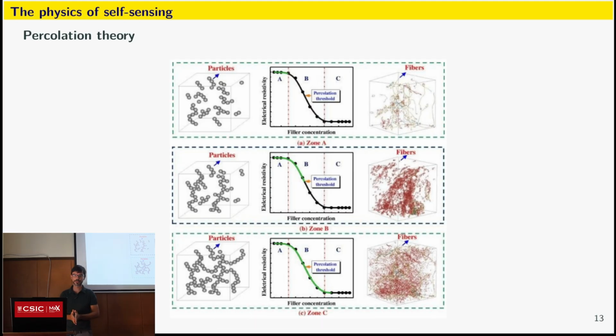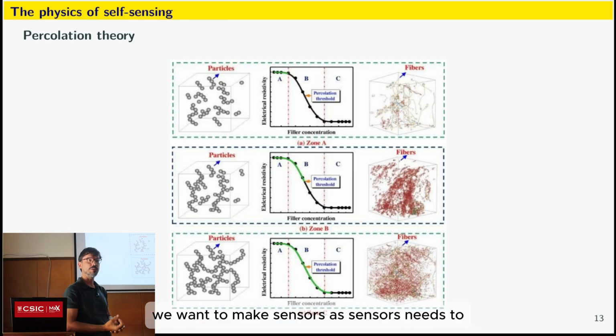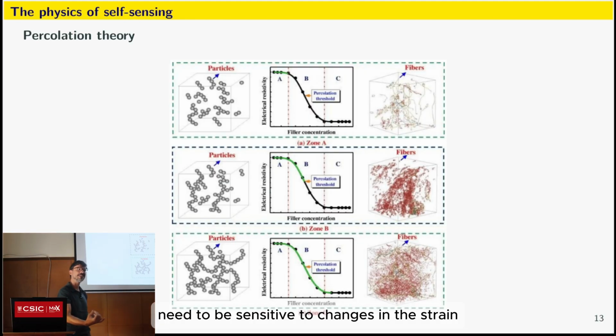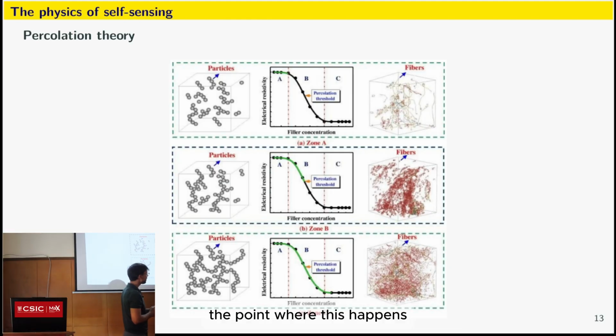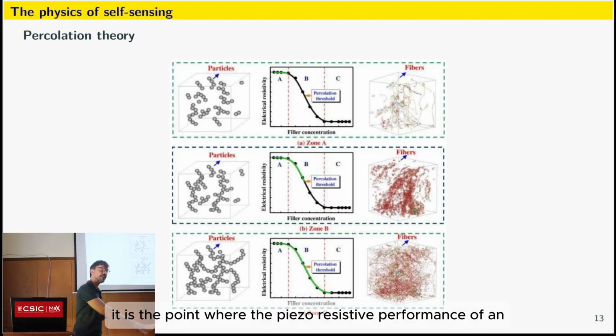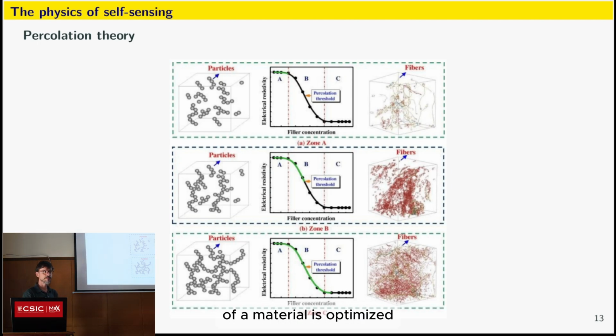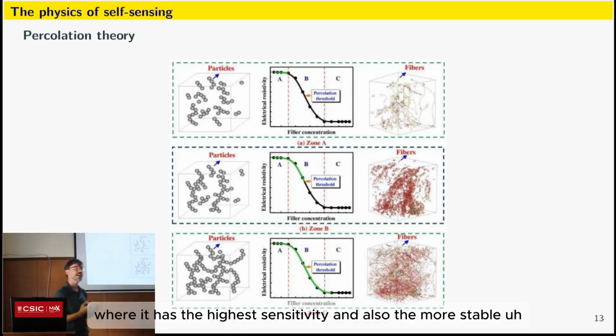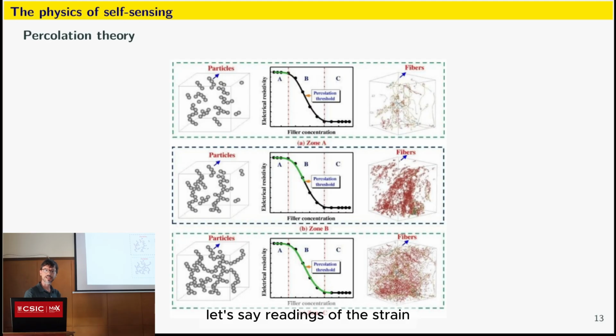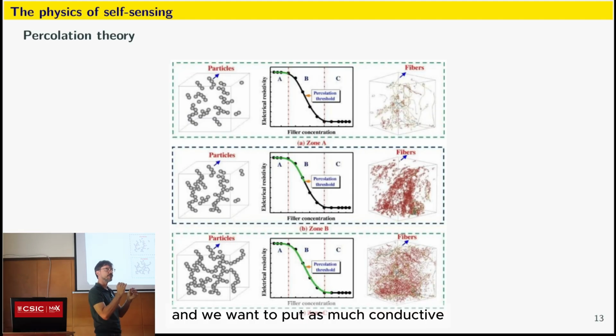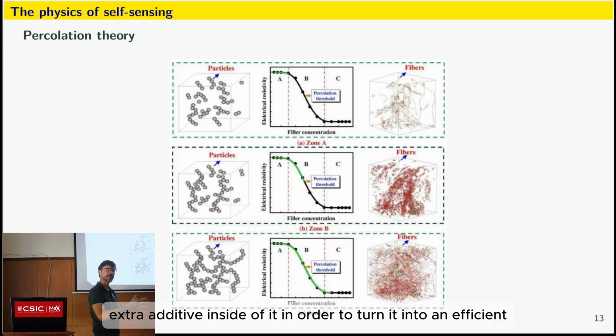But we do not want to make electrical conductors. We want to make sensors. And sensors need to be sensitive to changes in the strain. The point where this happens is what we call the percolation threshold. It is the point where the piezoresistive performance of a material is optimized. It is where it has the highest sensitivity and also the more stable readings of the strain. So we want to achieve that. We want to have a virgin material and we want to put as much conductive additive inside of it in order to turn it into an efficient sensor.